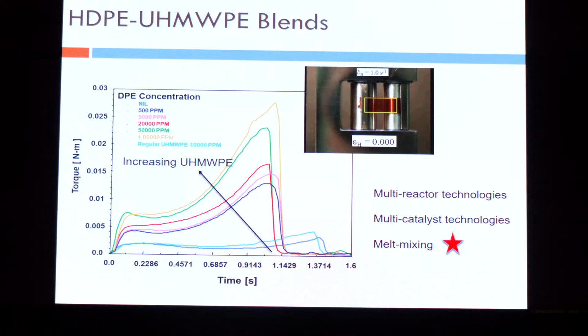I have to apply more force to stretch the film, and it also retains quite a bit of its ductility. So you get very interesting and important properties. If I want to make a film which is tougher, which can survive more strength, I can dose a little bit of the high molecular weight polyethylene into the low molecular weight polyethylene. And these are not very high percent, they are less than a percent. Okay, less than a percent, maybe less than 5% of the ultra high molecular weight into